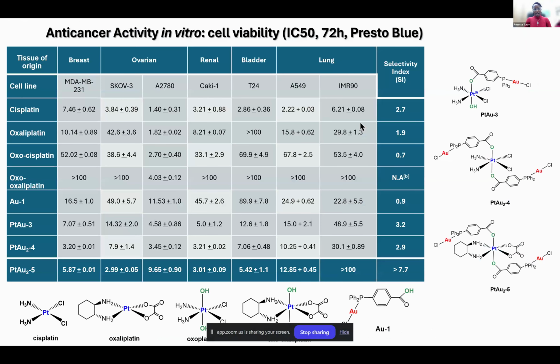Now, considering that, we saw that we had a variety of results. We saw the best results with our trinuclear model with the oxaliplatin core, where we have IC50 values of 5.87 in breast cancer, 2.99 in ovarian, and we found that it had the best selectivity index, meaning that there was a reduction of the unwanted side reactions causing side effects. Because we saw good results with our PtAu2-5 compound, we decided, let's try it with the carboplatin core.